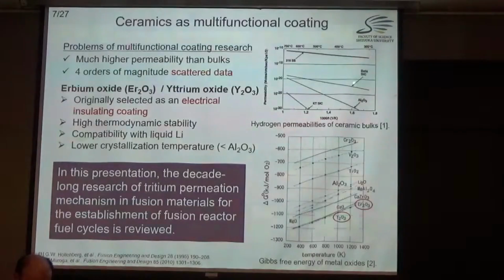Then we started using erbium oxide. So it's a rare earth metal oxide, and yttrium oxide, to make a really clean, pure, flat, uniform coating. And it was originally selected as an electrical insulating coating, and it has high thermodynamic stability. So this figure shows the free energy of the metal oxide. So it means really stable at a high temperature or in some corrosive environment. Then compatibility with liquid lithium. This is an alkali metal. And the good thing is the lower crystallization temperature than aluminum is also good.